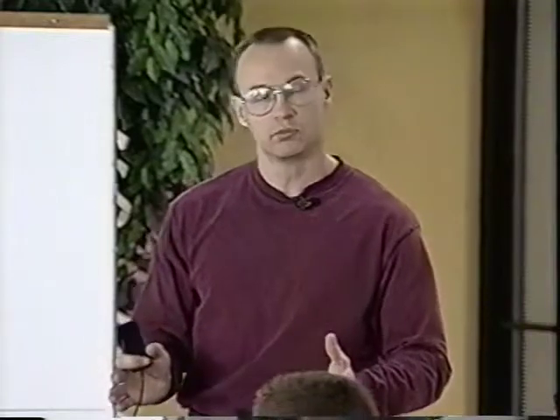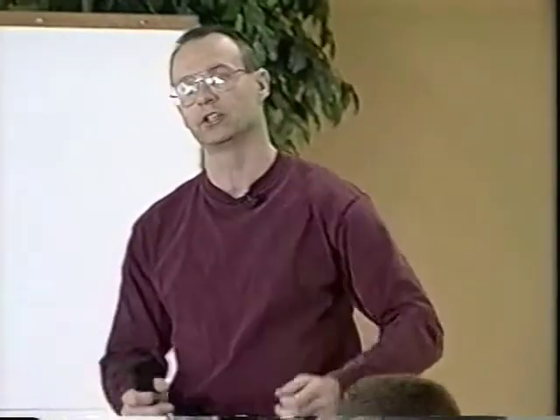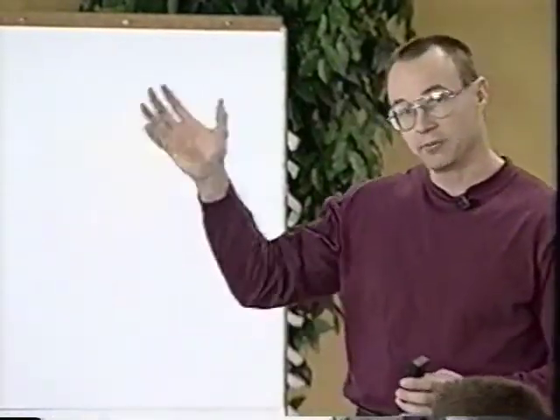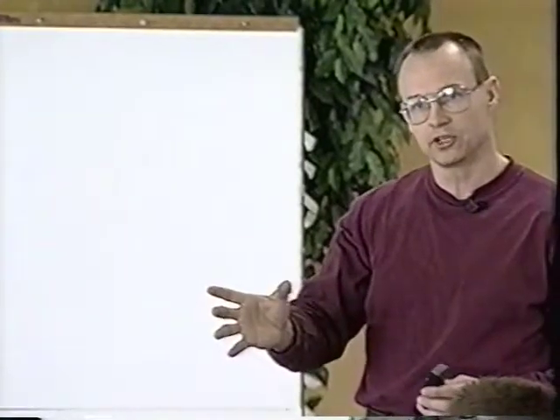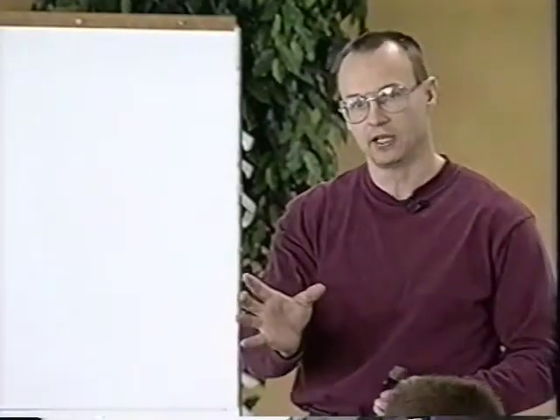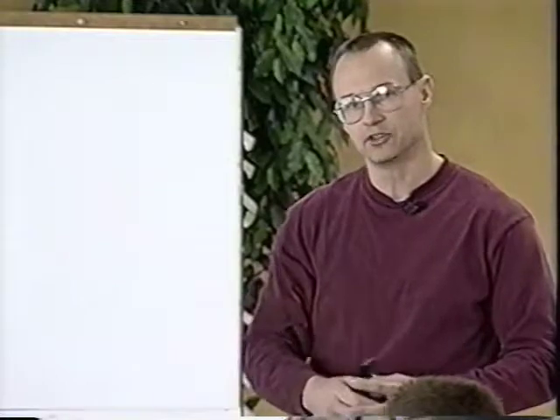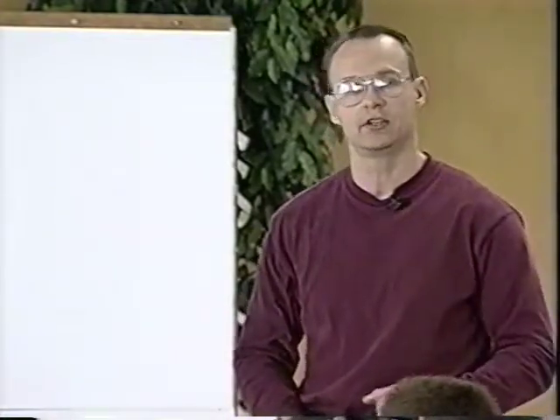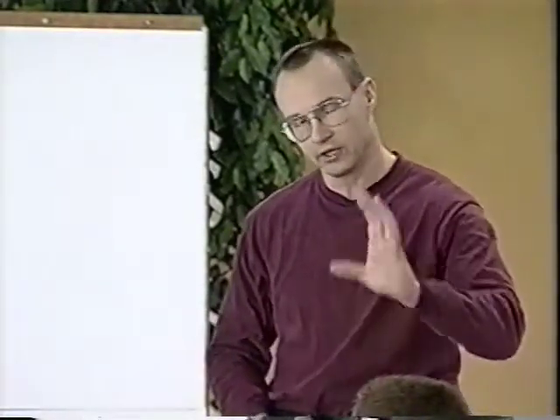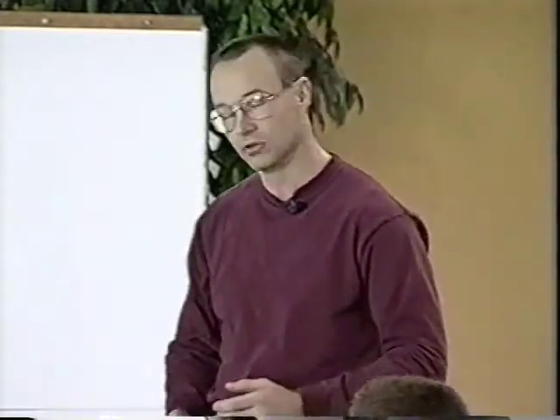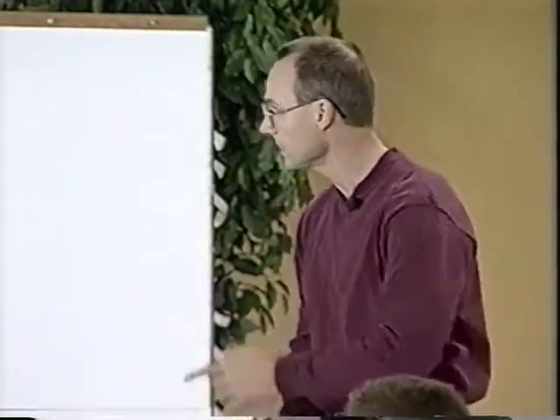And we have to bring this temperature up. In this whole process, we're generating heat. And we need to bring our temperature up from about the 2,500 degrees we're getting from the blast furnace up to about 3,000 to 3,100 degrees in the furnace. Because when we dump it out into the ladle, we lose some temperature. And then when we process it in our shop, we lose some more temperature. And we have to be about 2,800 degrees when we get to the caster, because if we're any lower than that, it'll start to solidify on us long before we want to.